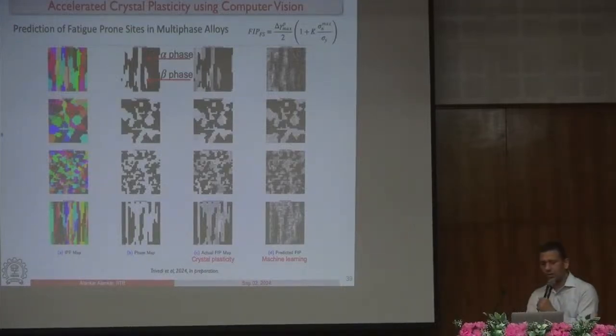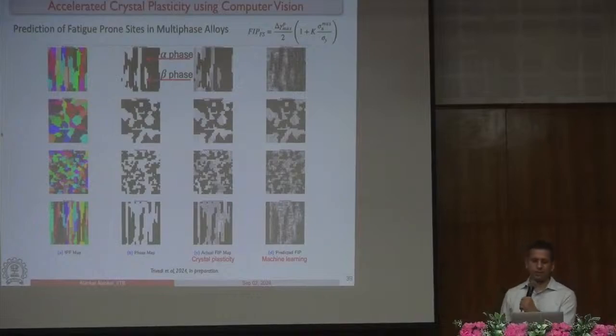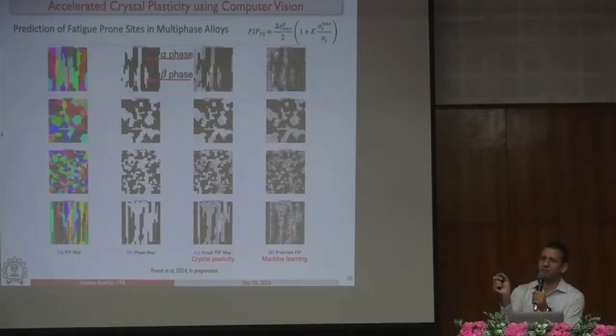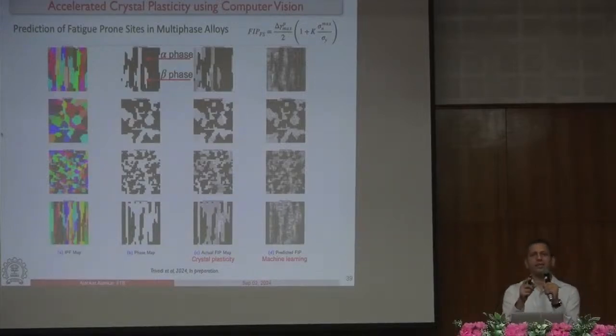All right. The almost second to last example: in the beginning I showed you that we have this physics-based fatigue model, which has plasticity, elasticity. We can take it through various number of cycles, and it tells in the microstructure which part of the microstructure or grain or phase is more prone to fatigue. Now, I said that still we have to run 3 cycles of simulation, which are still expensive. It takes about a day to run those 3 cycles. We produced about 8,000 such simulations because we needed them anyway.